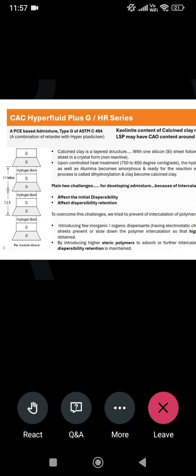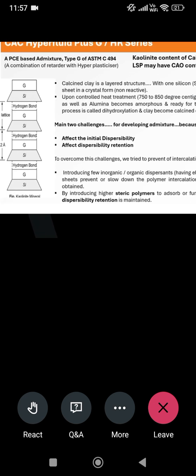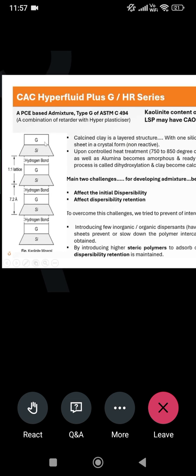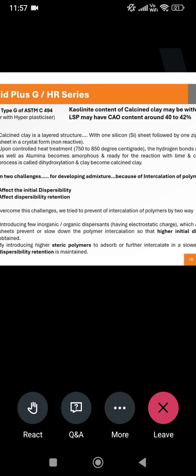One sheet is alumina and the other is silica, and this group of sheets is bonded with a hydrogen bond. It is a raw clay, and it needs to be treated because the silica and alumina are in crystalline form. They are not reactive. To make it reactive, it needs a heat treatment. When we heat to 750 to 850 degrees, the hydrogen bond between these sheets is broken, and the sheets get foliated, with more space between layers. Now it is still a layer by layer structure, but there are more layers, and all the alumina and silica are converted to the amorphous, reactive form. These two things are happening.